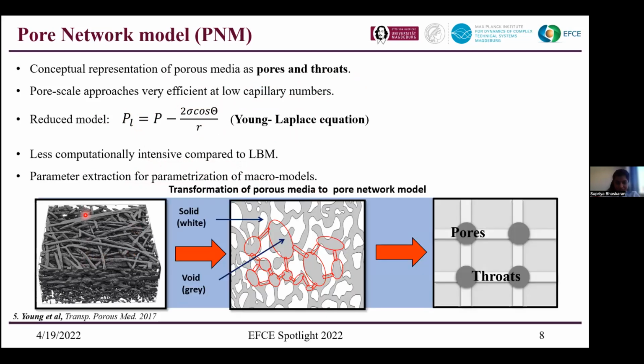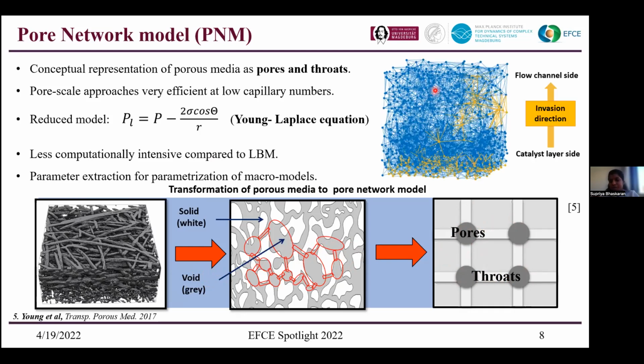So here we have our fibrous network, and we first differentiate between our solids and void spaces. So once we have these void spaces, we mark those voids and the connections between the two pores via the throats. So, and then we consider our pores and the throats. So this is a simple idealized network, but in real it looks something like this, where we get the exact pores and throats connected in an irregular network. And then we assume a catalyst layer side at the bottom, and then we have a flow channel at the top side. And we have the invasion from the catalyst side to the flow channel.